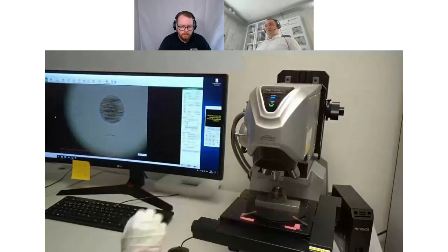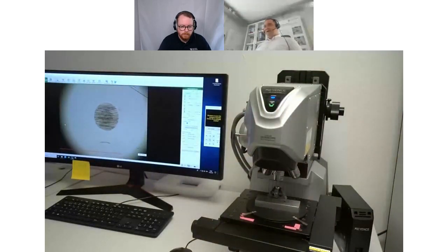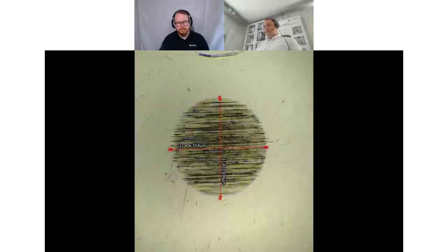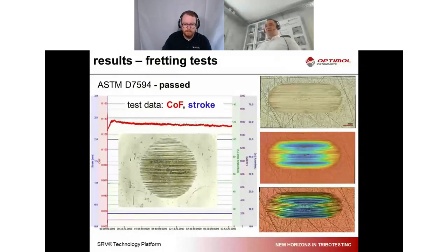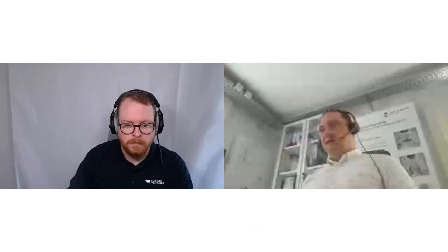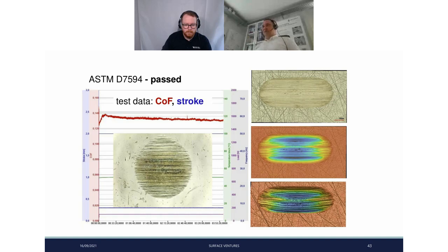And then, of course, you need a good microscope to take the picture of the wear scars. In our case, we are using a laser scanning microscope, which makes it very easy to measure the wear dimensions. On the one hand side, the diameter of the wear scar, for example, and on the other hand side, we can easily then evaluate the wear volume on the counterpiece, on the disc. And this gives you then, together with the COF, coefficient of friction, three simple values which characterize the anti-fretting performance of your test system, or of your samples.